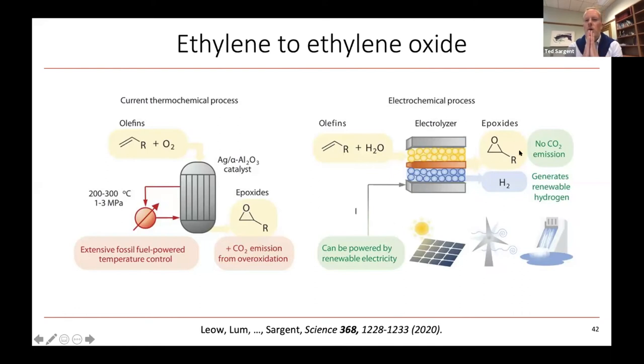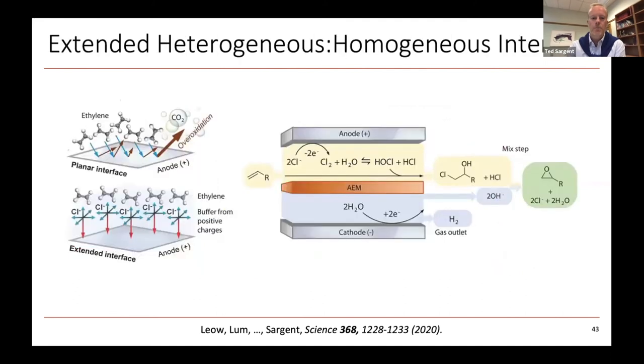And what we found in a very recent system study is that we were able to use an approach in order to get to epoxide, so ethylene oxide in this case, where we could overcome the very large carbon footprint that is seen in ethylene oxide production today through thermocatalytic routes, which really comes from a lack of selectivity. So quite a bit of the ethylene that's being oxidized to ethylene oxide today ends up going all the way to CO2, instead of being very selective and just taking it to ethylene oxide.